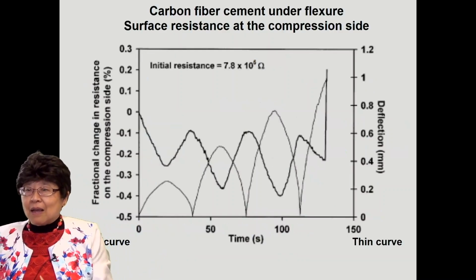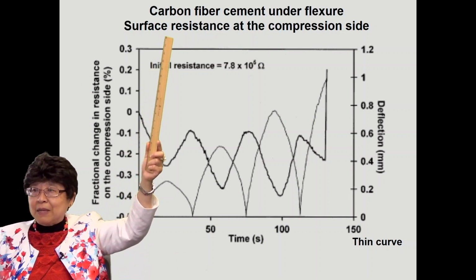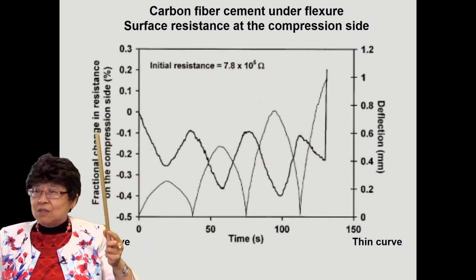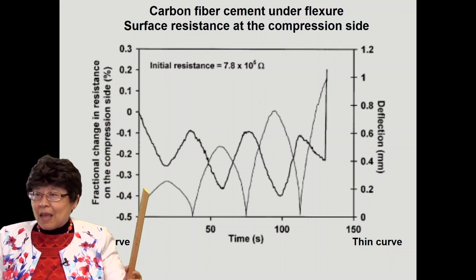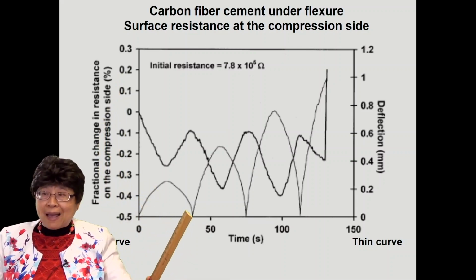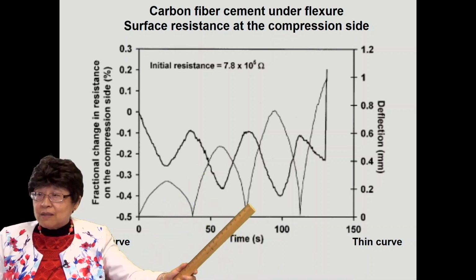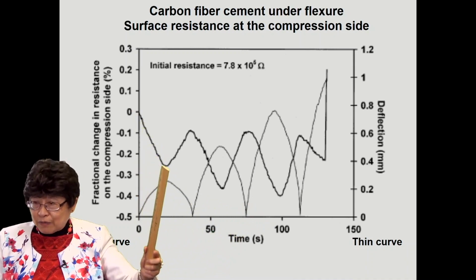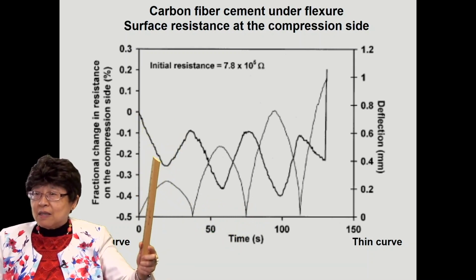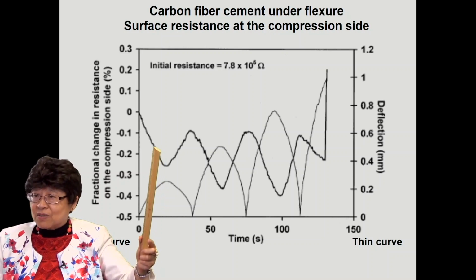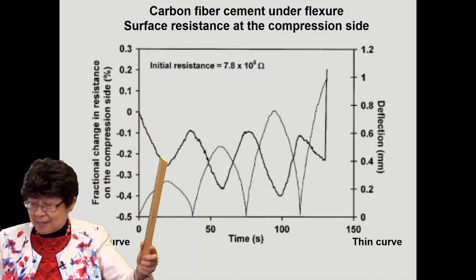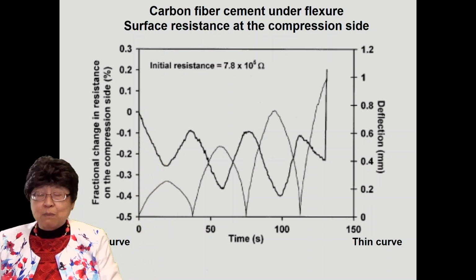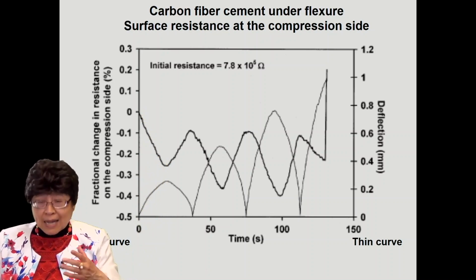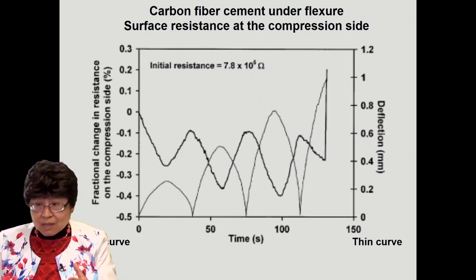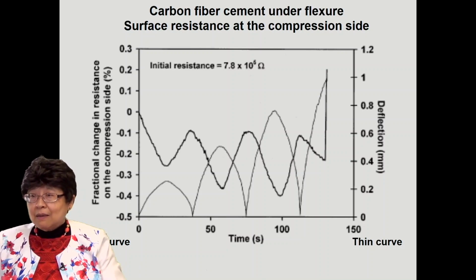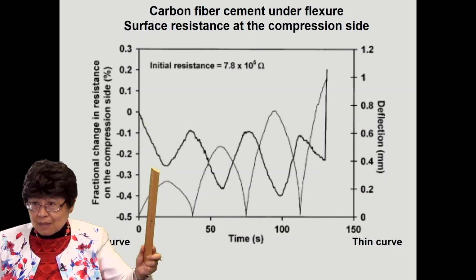And using this method, I looked at carbon fiber cement again, but under flexure. And this is the surface resistance on the compression side. The thin line is the mid-span deflection. It's a gradually increasing degree of bending. And the thick curve is the fractional change in the surface resistance on the compression side. And it decreases every time you flex it. Okay? And that agrees with what we observe under uniaxial compression, which again involves the resistance decreasing as you uniaxially compress. And here on the compression side, again, it decreases.